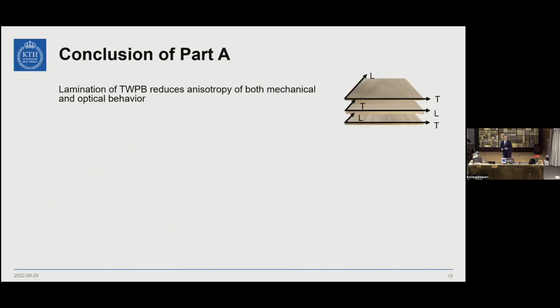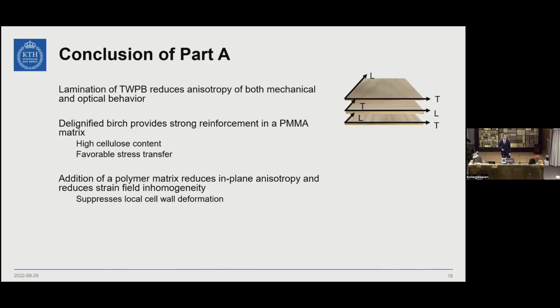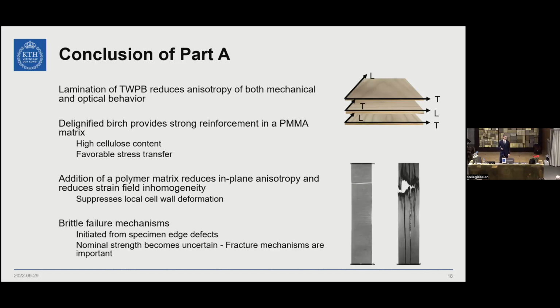So the conclusion of part 1 or part A is that we can use lamination to reduce anisotropy. We have a better reinforcement effect by choosing the delignified birch, and adding a polymer reduces the in-plane anisotropy. But we have a brittle failure. So this failure mechanism is what we will investigate in the end, in part C.